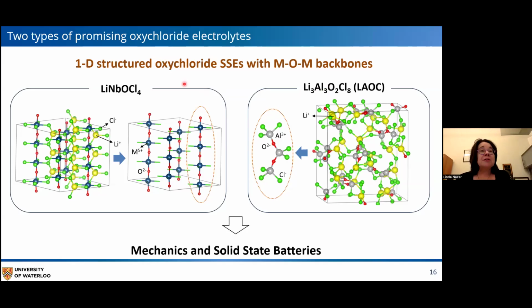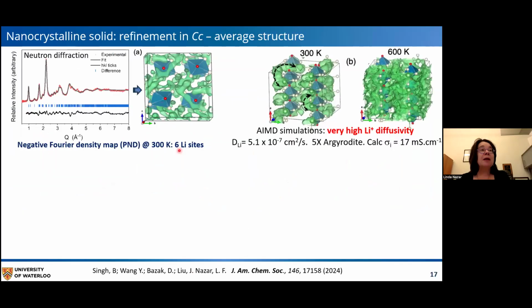So we were quite curious about this material that was reported by the Panasonic group, and so we decided to repeat the synthesis of the material, and we were able to achieve the same conductivity that they did, upwards of 11 millisiemens per centimeter. And you can see from the neutron diffraction pattern that this is a nanocrystalline material. The peaks are quite broad. We still can do a Rietveld refinement, but it's kind of an average structure.